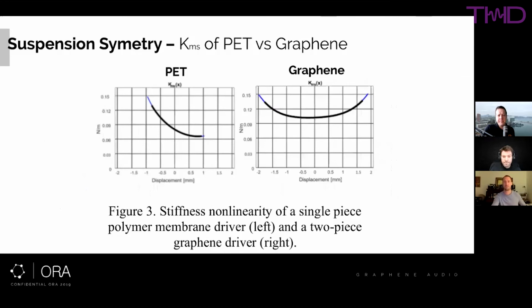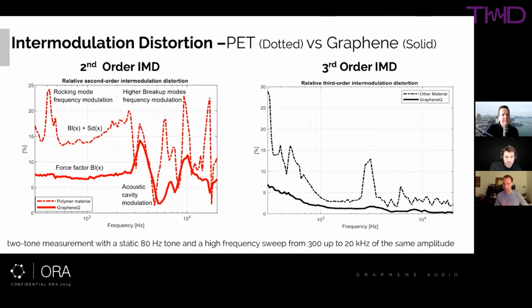And if you look at the intermodulation distortion, the difference between the two drivers gets even more stark. The dotted line is the polymer, and the solid line is the graphene, for second and third order intermodulation distortion. In the second order, the graphene is much lower than the polymer, and this distortion exists throughout the audible bandwidth. For the third order, we have almost none relative to the polymer membrane. And that definitely affects your listening. When your brain has to listen through all that distortion, it takes a lot of mental energy. Even if you're not specifically hearing it as distortion, it takes its toll on your attention and your ability to hear detail in the sound.